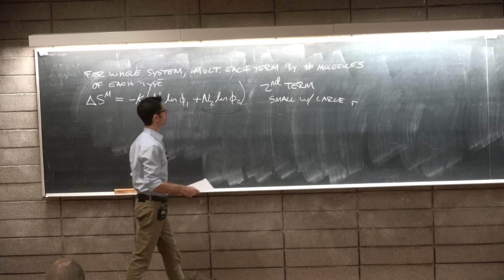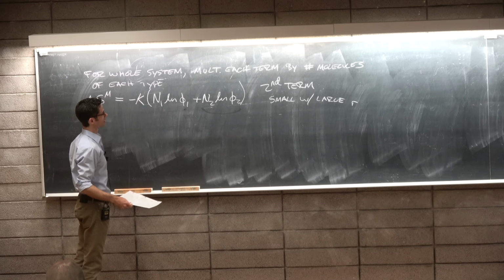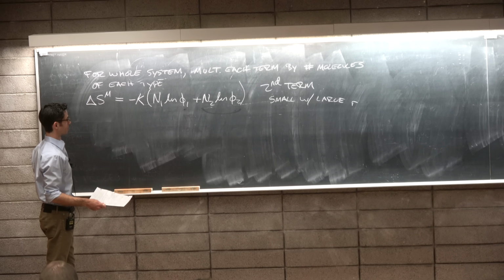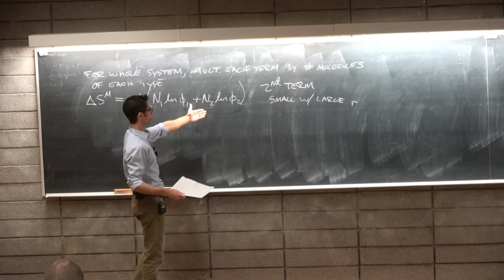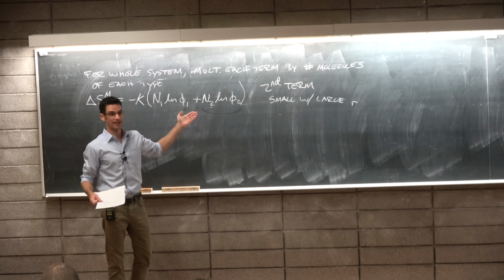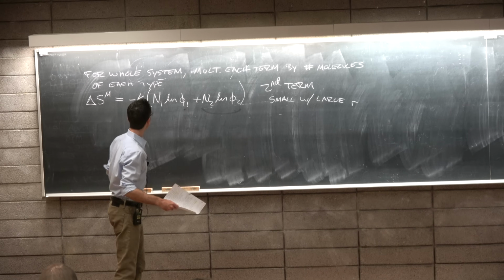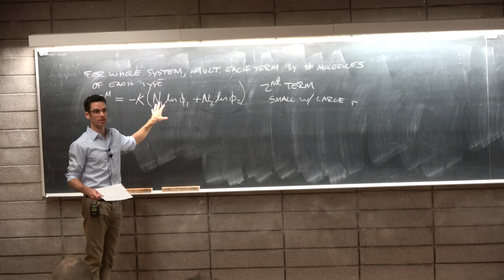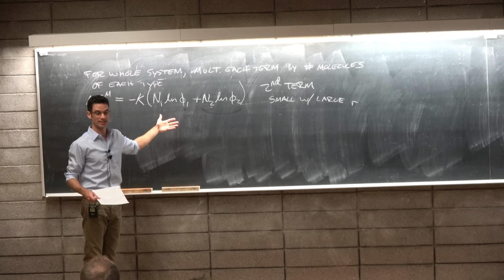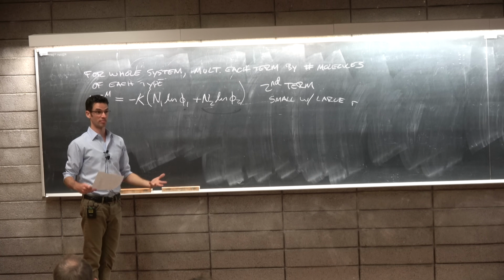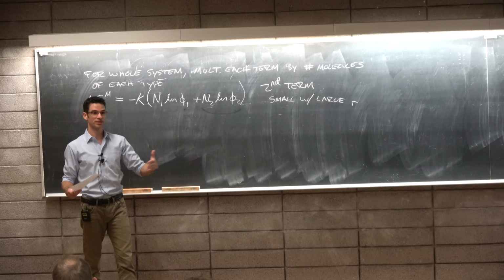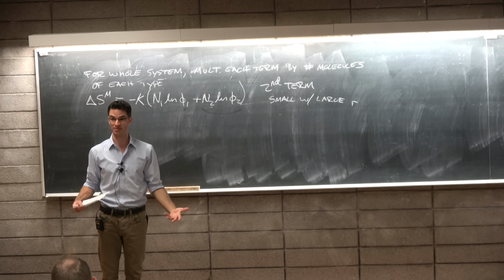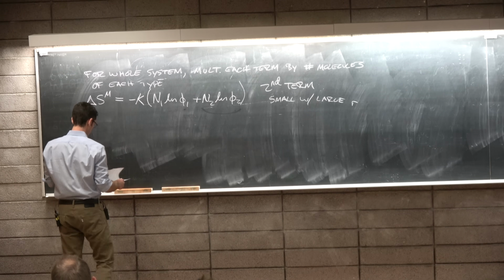So it becomes smaller with large R because phi approaches 1, and also the number of polymer chains decreases. So then you have only the entropy of mixing due to the solvent that's contributing to the favorable entropy of mixing of the entire mixture. So just by increasing the length of the polymer chain, you make it less soluble, you make it less favorable to mix.